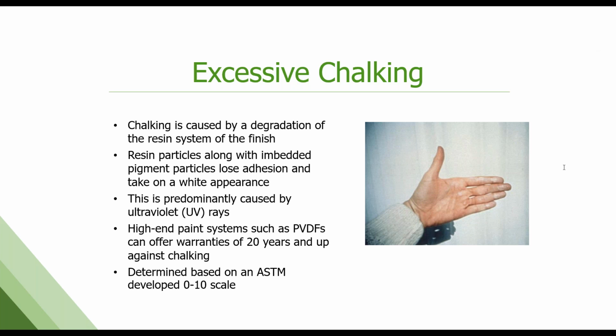So what is chalking? It's just what you think it is. It's a chalky surface after exposure. So it's a degradation of the resin system. That polymer resin backbone starts to break apart into little pieces because of exposure to UV. When that happens, it can now come out of the paint surface, bringing pigment with it. So you get this white appearance. It's caused by UV. I rarely see this anymore. Even in polyesters, the formulation work has gotten so good, the polymer technology has gotten so good that we rarely see excessive chalking anymore, just few and far between. There is an ASTM test to measure it. You don't use just your hand. There is a way to measure it out in the field. Next slide.